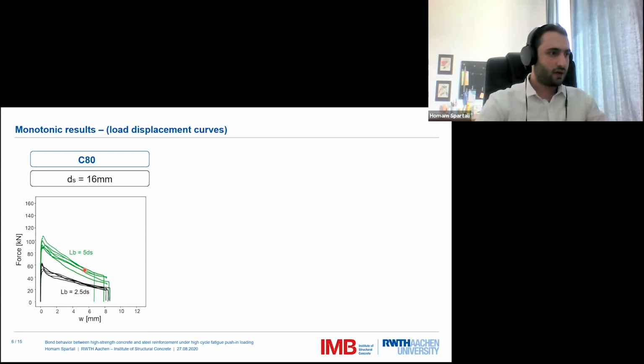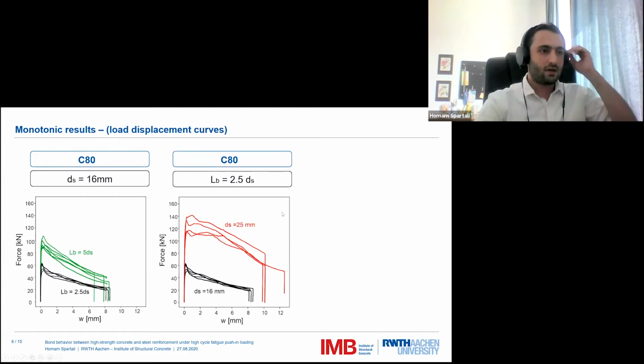The green curves are for the bond length 5 ds and the black curves for the bond length 2.5 ds. We see that by doubling the bond length, we almost also double the maximum reachable force, or the bond maximum reachable force. In this other diagram, we see a comparison between the results for the 2 different bar diameters, 25 millimeters and 16 millimeters from the same concrete and bond length.